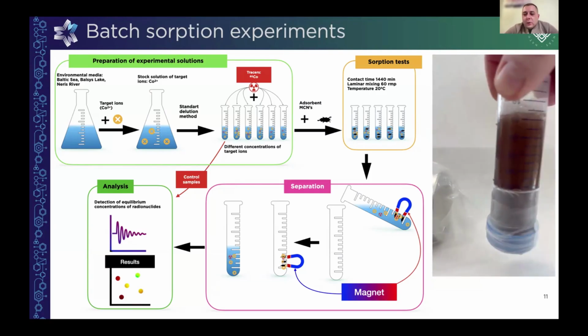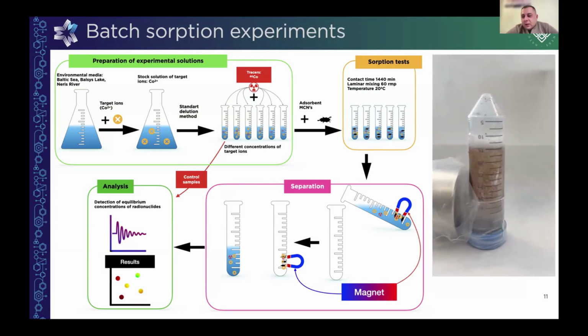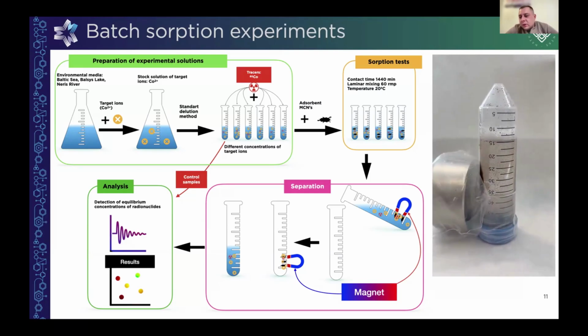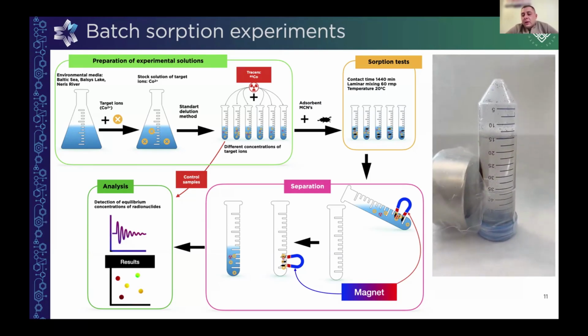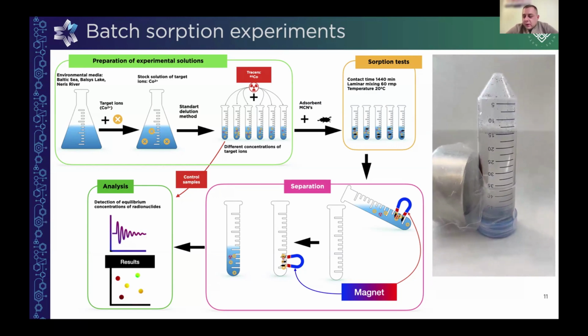and then we added some amount of cobalt-60 tracer, and after changing the experiment parameters like time or concentrations, we separated the sorbent with a magnet and measured it with the gamma spectrometer to detect the changes in concentrations. Also on the right, you can see how it works in the sample. It takes less than 30 seconds to ensure good separation of magnetic chitosan 30. For magnetic chitosan 10 and 20, more time is required, but it still works very well and can be used in such a strategy to collect it from different samples, liquids, and so on.